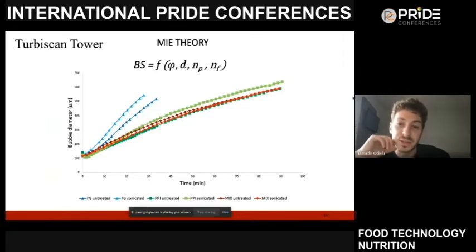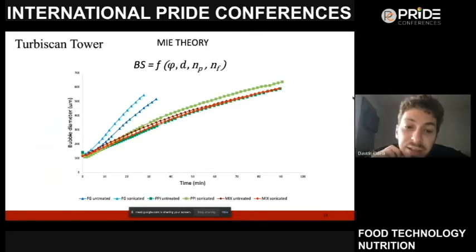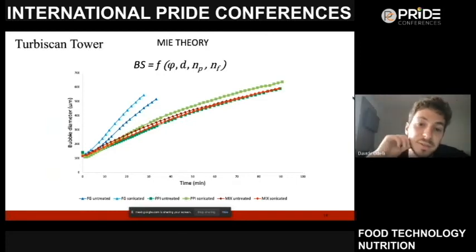Here, from these results, we can conclude that both the mixed proteins and the P proteins steadily increase their bubble diameter, but overall maintain a really good stability over the 90 minutes considered. While it wasn't the same for the fish gelatin foams, because their air bubbles increased rapidly until they reached a limit and burst around 25-30 minutes.